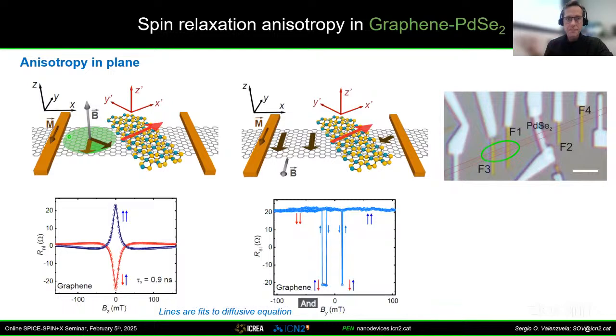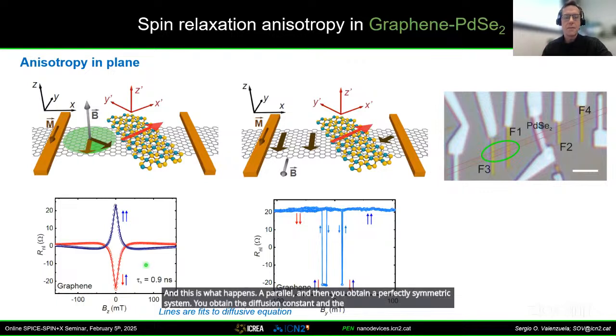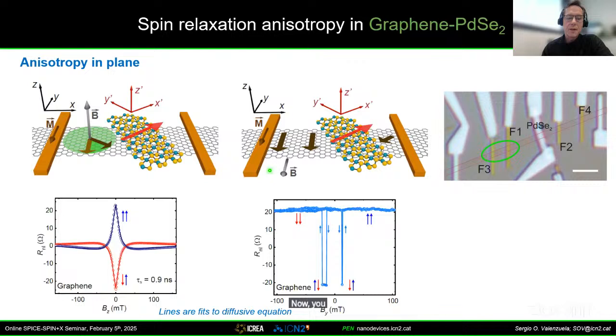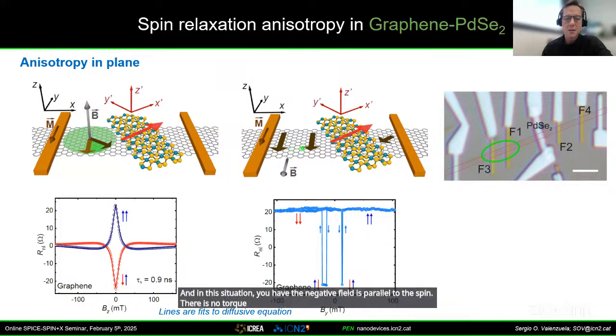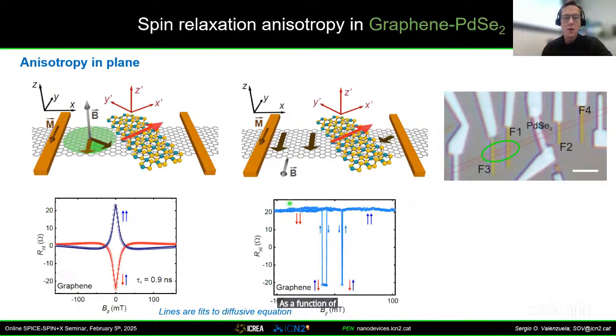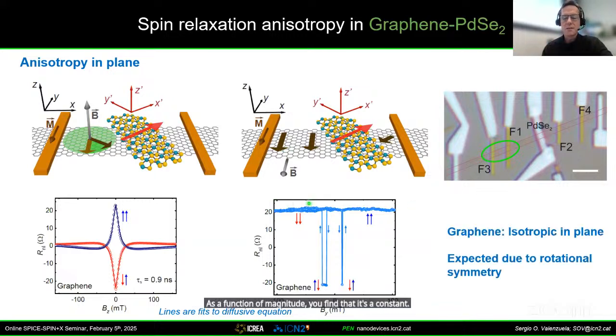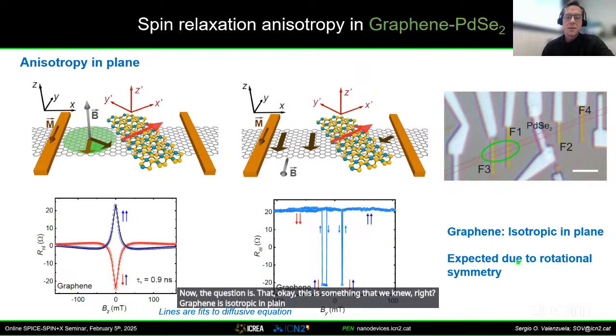And this is what happens. They're parallel, and then you obtain a perfectly symmetric system. You obtain the diffusion constant and the spin lifetime in this region. Now, you can also apply a magnetic field along the injection direction. In this situation, the magnetic field is parallel to the spin. There is no torque on the spins. There is no precession. As a function of magnetic field, you find that it is a constant. Now, the question is that, okay, this is something that we knew, right? Graphene is isotropic in plane. This is due to the symmetry of the material, and that's it.